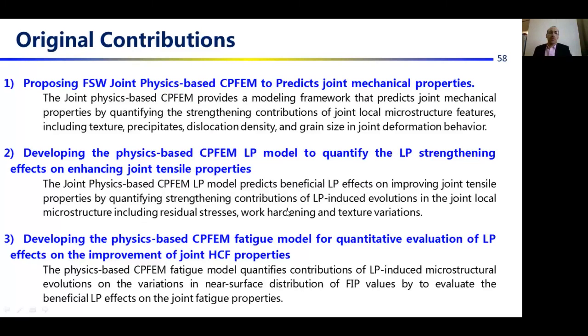Now for the summary and the future work, original contributions of this work include proposing FSW joint physics-based CPFEM to predict the joint mechanical properties by quantifying the strengthening contribution of joint local microstructure features, including texture, precipitate, dislocation density, and grain size. And the second one is developing the physics-based CPFEM laser peening model to quantify the laser peening strengthening effects on the enhancing joint tensile properties by quantifying the strengthening contribution of laser peening induced microstructural evolution such